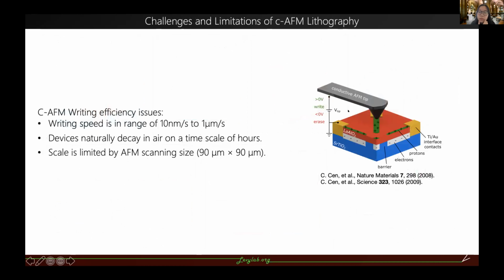But as we're taking advantage of the conductive AFM lithography, we're also facing the limitations it has. So I summarized these into writing efficiency issues. For conductive AFM lithography, the writing speed is in the range of 10 nanometers per second to 1 micrometer per second. At the same time, the device itself decays naturally in the air on the timescale of hours. So these two conditions restrain the complexity of the device we could make. The writing scale is also limited by the AFM scanning size, which is 90 by 90 micrometers at the largest.